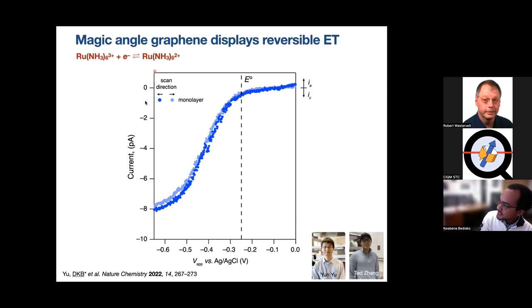reaction. So if we take a monolayer of graphene and we sweep this voltage, this is what we see. We see this blue curve, the dark moving forward, and the lighter trace in the reverse. So you see this S-shaped curve that is offset from this potential that I've depicted as E0, which is simply the thermodynamic potential of this redox couple. It is where this redox reaction should proceed thermodynamically, reversibly. However, you can see that the midpoint of this S curve is offset from that, and that is because the kinetics are slow.